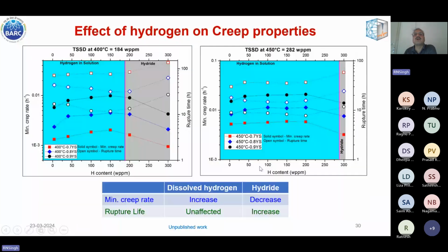Now, another plot is for creep properties, the effect of hydrogen on creep properties. Here, this test is still our unpublished work. We have been able to complete this test only at 400 and 450 degrees Celsius. Again, the same color code has been followed. If you see that cyan color region, here again dissolved hydrogen is increasing the minimum creep rate marginally. And in the case of hydride, it is reducing the minimum creep rate. Here in the case of 450 degrees Celsius, the effect is not much, almost horizontal lines are there.